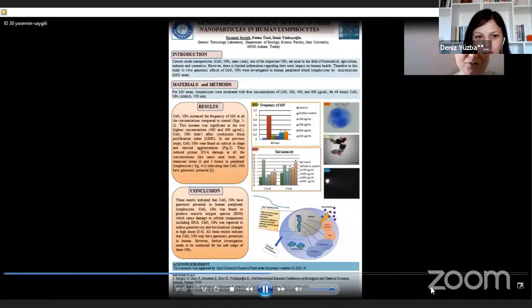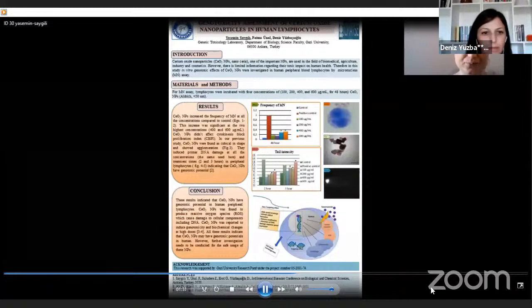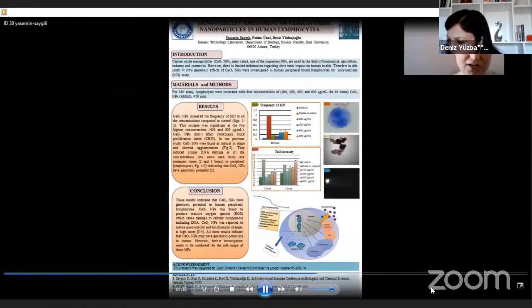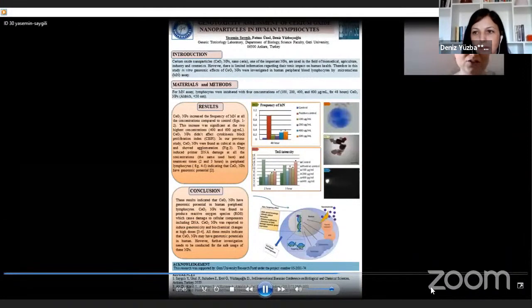In our previous study, cerium oxide nanoparticles were found as cubical in shape and showed agglomeration. They induced primary DNA damage at all the concentrations and treatment times in peripheral lymphocytes, indicating that cerium oxide nanoparticles have genotoxic potential. These results indicate that cerium oxide nanoparticles have genotoxic potential in human peripheral lymphocytes.